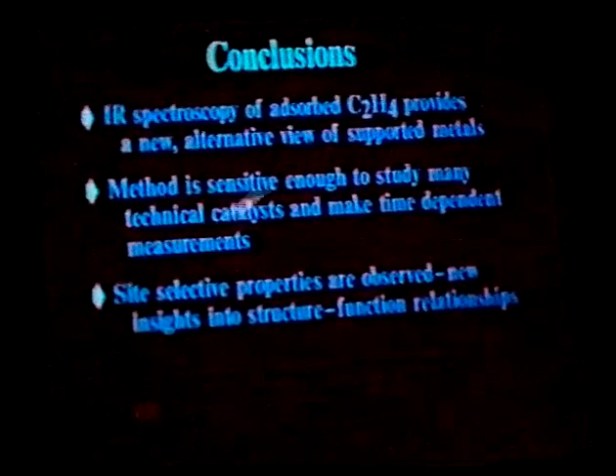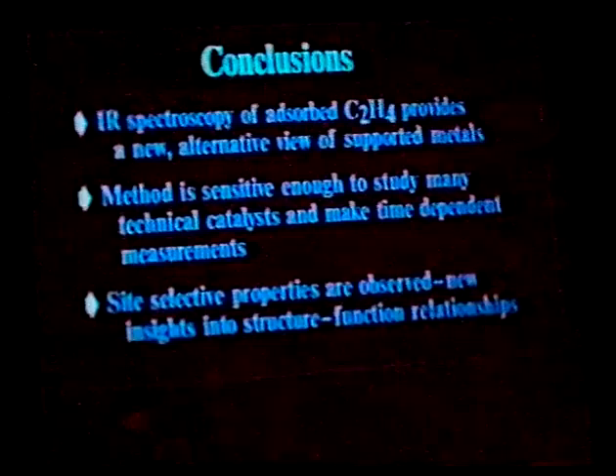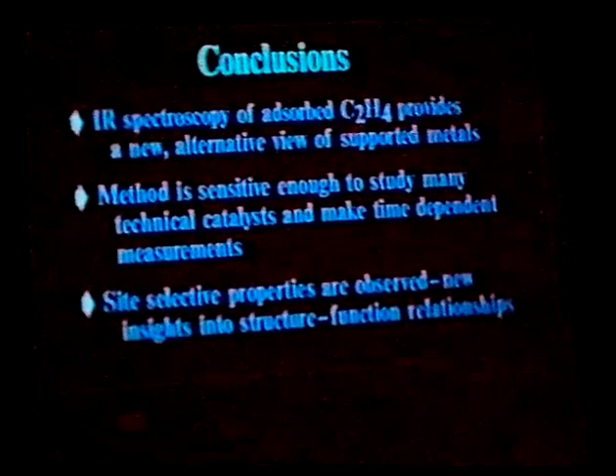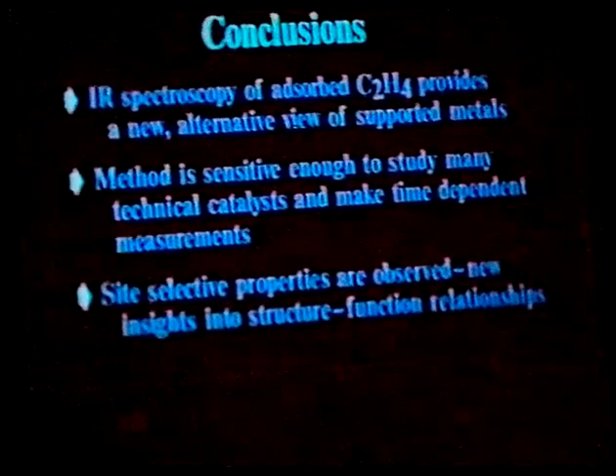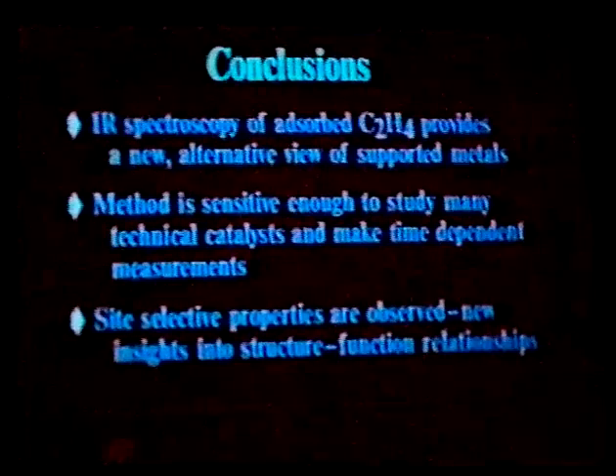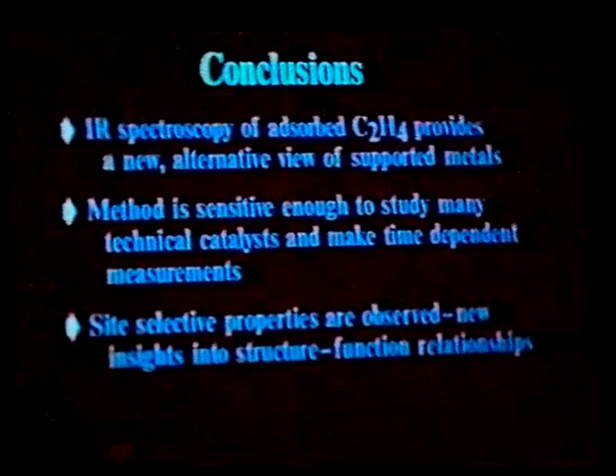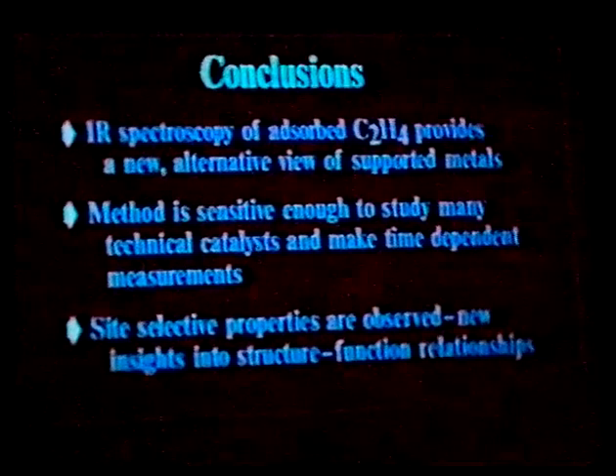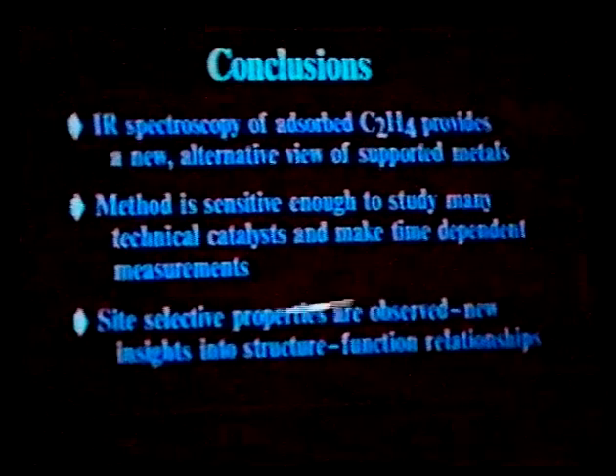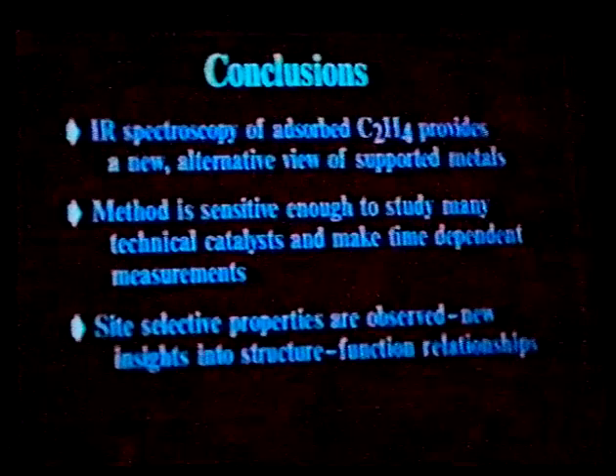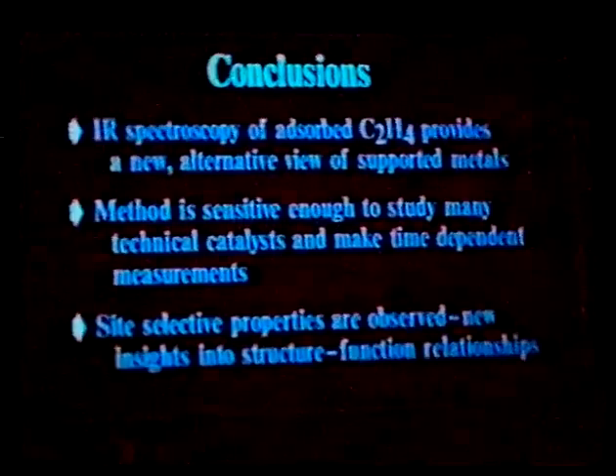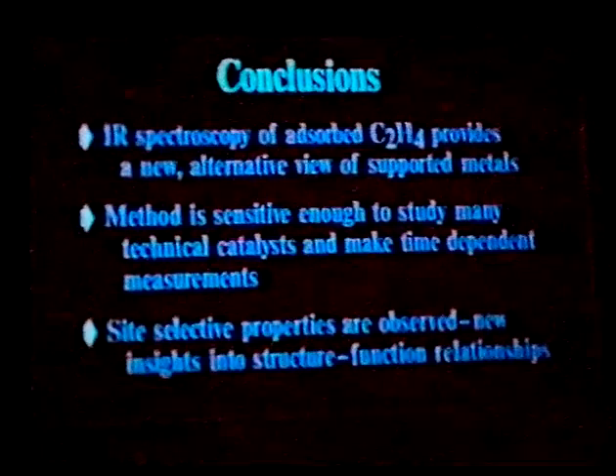But the method is sufficiently sensitive to study many kinds of technical catalysts. I think that for the 1% platinum catalyst that I showed you, the signal to noise there is quite adequate, and that you can probably go to considerably lower weight loadings and still get very good spectra. And then finally, that there are site-selective properties that you can observe with ethylene as a probe molecule, and it would be interesting to try to exploit this.